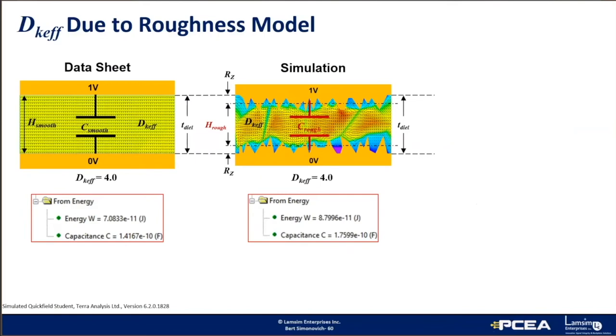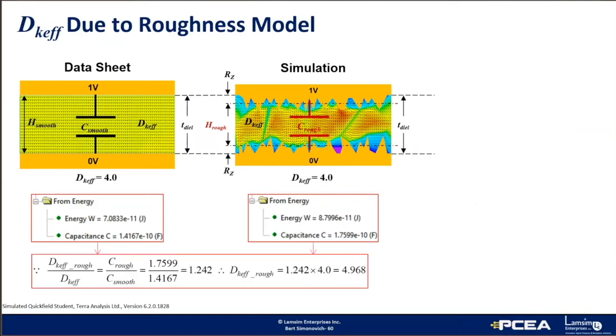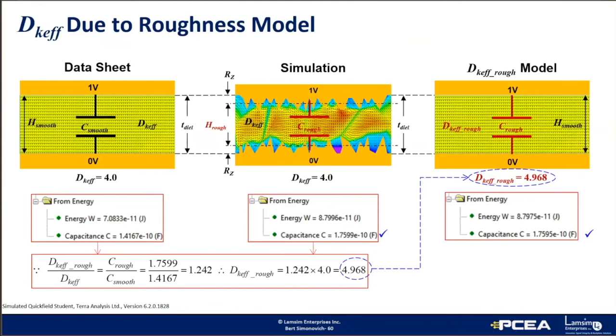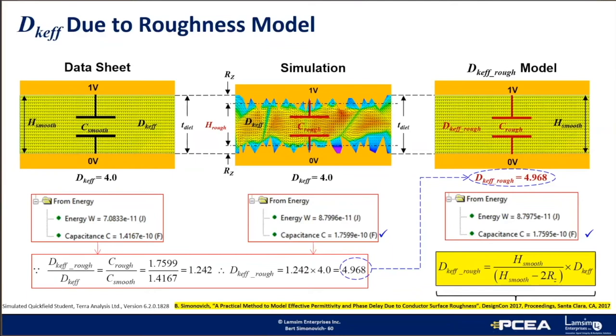The effective height, H rough, can be approximated as H smooth minus 2Rz. The ratio of Dk effective rough to Dk effective equals the ratio of C rough to C smooth. With a little bit of math, we can calculate Dk effective due to the roughness as 4.968. And when we use this number in a new smooth foil model, we get the same effective capacitance of 175 pF. This model can be reduced to this simple equation. This is the effective Dk you need to use in your favorite field solver for characteristic impedance calculation if you know the roughness of the foil.